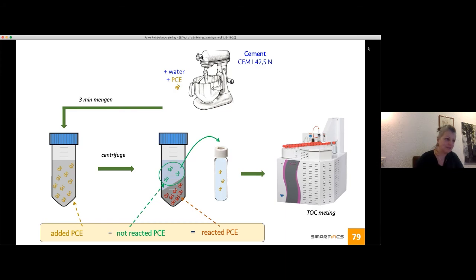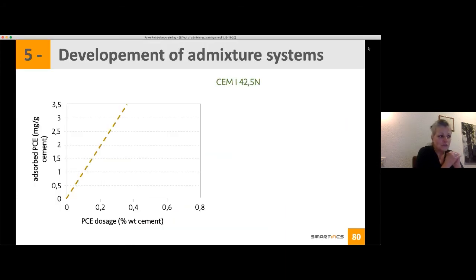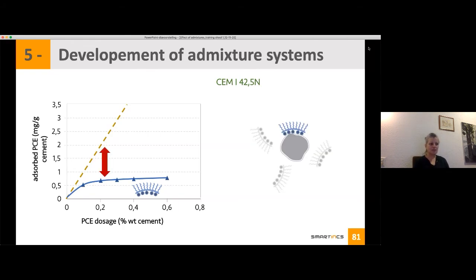Okay. So what we get from these measurements: here on the horizontal axis is plotted how much PCE I have put, so I have increased the dosage. And on the vertical axis, I measured how much has reacted. And ideally, if everything I put has reacted, I should be somewhere on this dotted line. Now I've tried a PCE, and this is the line that I get. So what I see is that theoretically, from the dotted line to my line, I have a big difference.